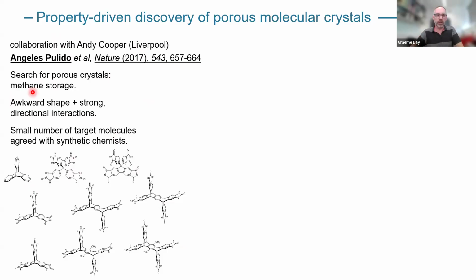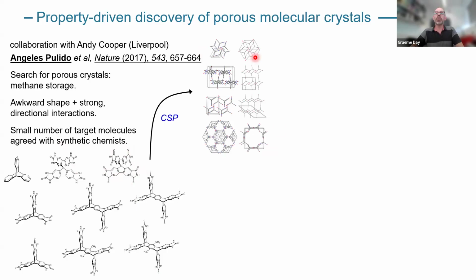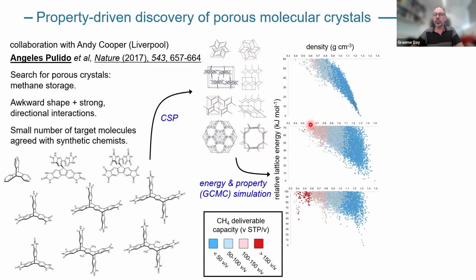So we're interested in materials for methane storage, maybe for a natural gas-powered vehicle. So the hypothesis in terms of design here was to look at awkwardly shaped molecules that have strong polar groups for hydrogen bonding on their corners, with the hope that those hydrogen bonding interactions will prevent these molecules from close packing, will leave gaps and give us porous structures. Each of those molecules, the synthetic chemists told us, would probably be weeks or months of work. So we don't want to do all of that in the lab. Instead, we do it by structure prediction. We generate all the potential crystal structures of each molecule. We energy minimize them. And now for each of those predicted crystal structures, we also calculate properties. Here, it's the amount of methane you can get in.